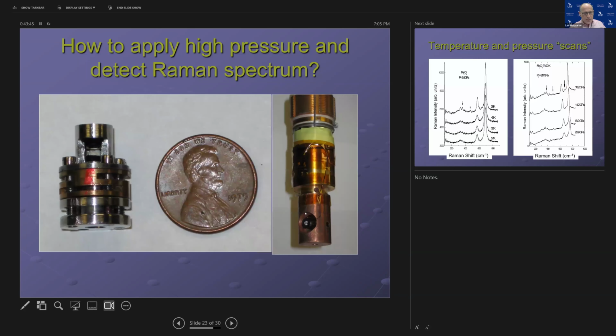His name is Viktor Struzhkin. He retired from the geophysical lab. So this is the setup that is a little bit different from what I showed, but it's very miniature, and it allows you to do pretty much the same. So this is the diamond anvil cell. You can barely see two diamonds here. This plate is a gasket. So that's the face of the cell. You shine light through the diamonds on the sample, and you collect light scattered from the sample and analyze it. And that's where you see your Raman scattering.